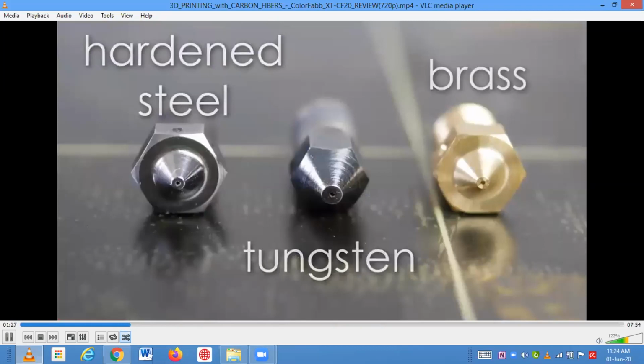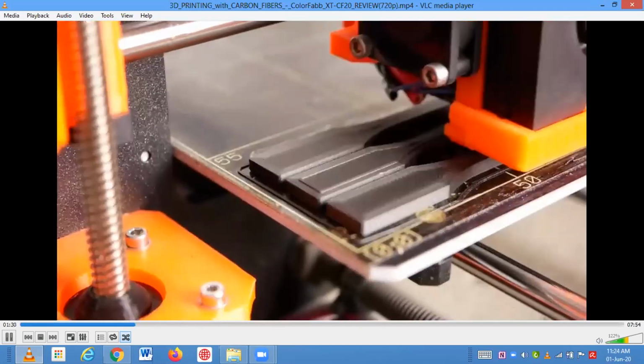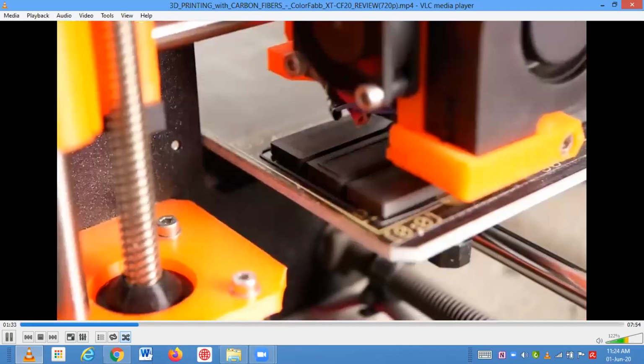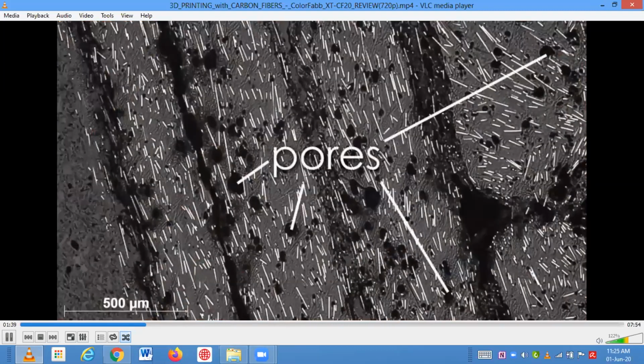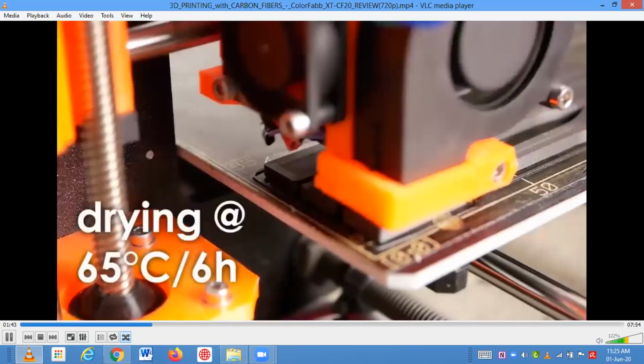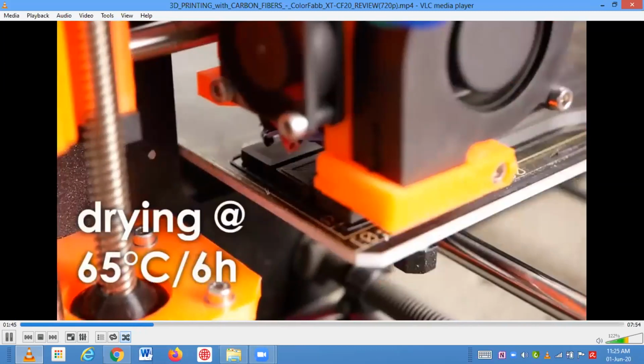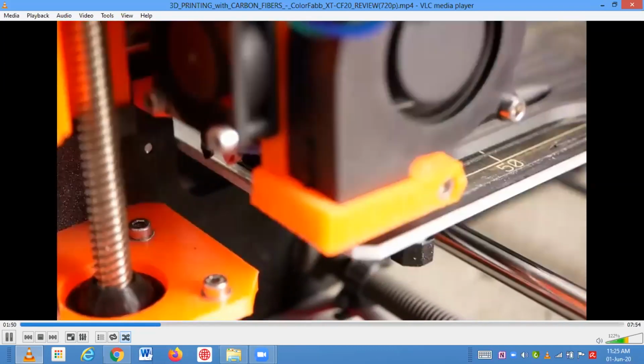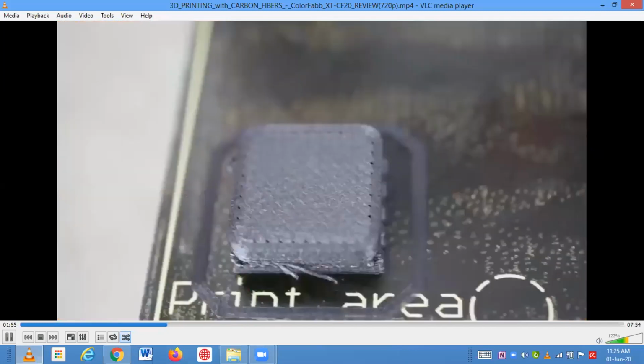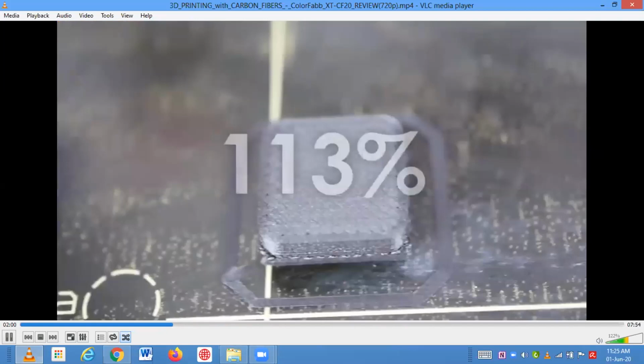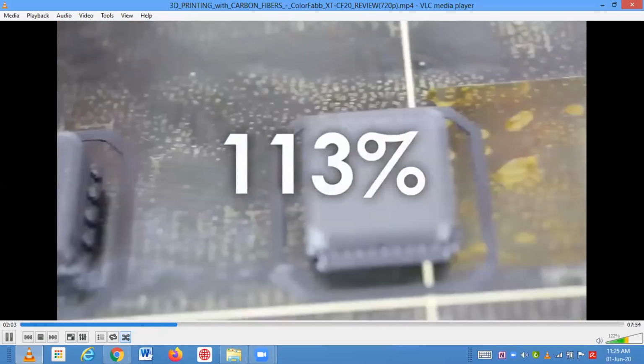Usually I print my whole set of test samples and then analyze them. Unfortunately, I noticed after the first run that the printed parts showed quite a lot of porosity, probably due to moisture, so I dried the roll of filament in my oven at 65 degrees Celsius for around 6 hours and reprinted all of the material test samples, and this filament test ended up to be way more effort than I anticipated. The first thing I noticed was that instead of an extrusion factor of 100%, I now needed to increase it significantly to 113% to get good prints.